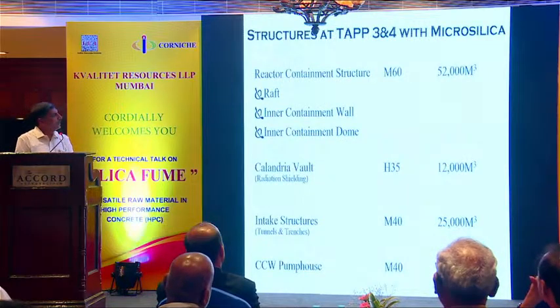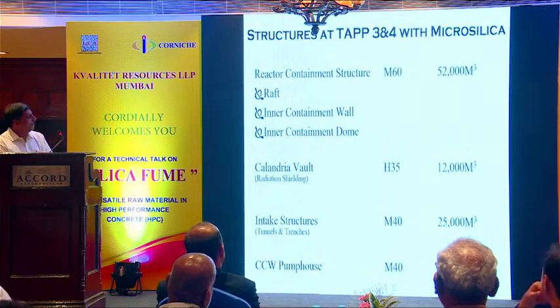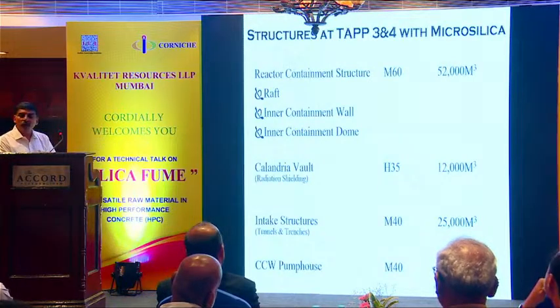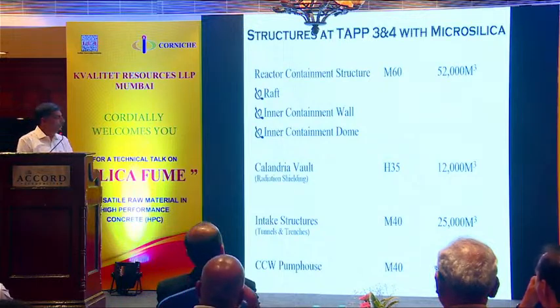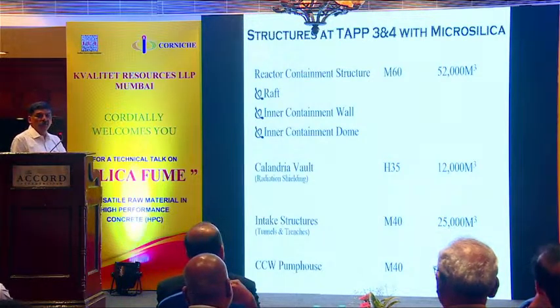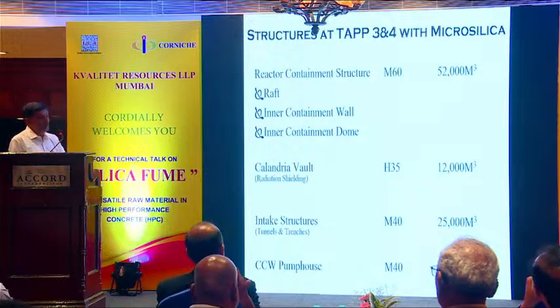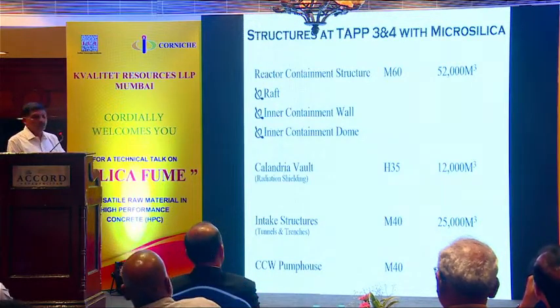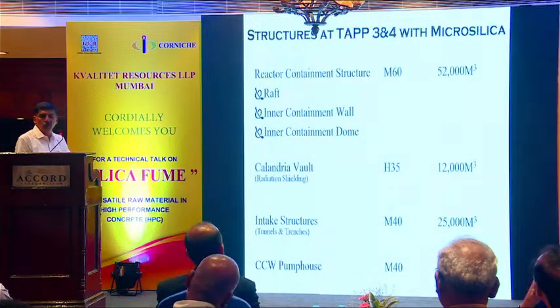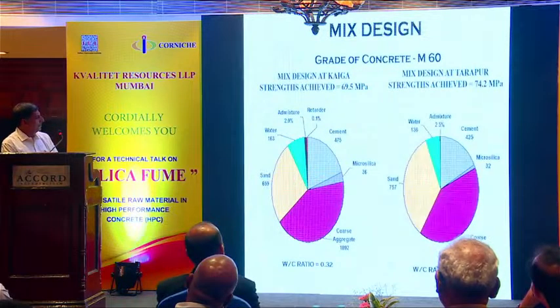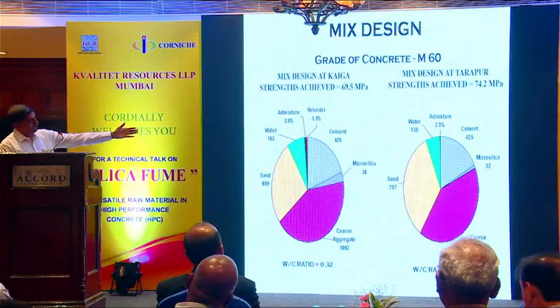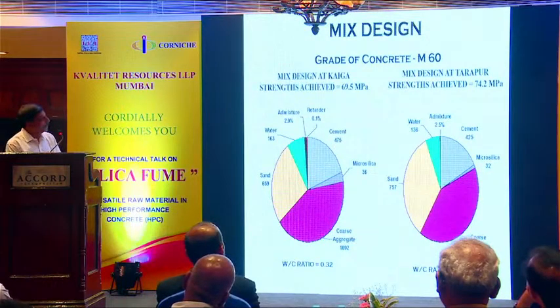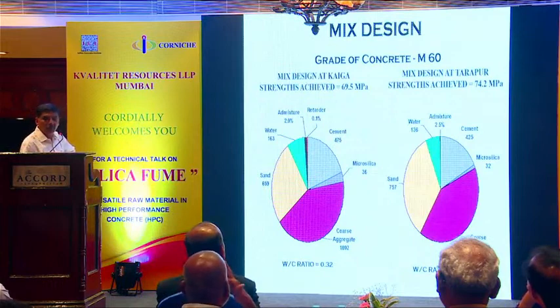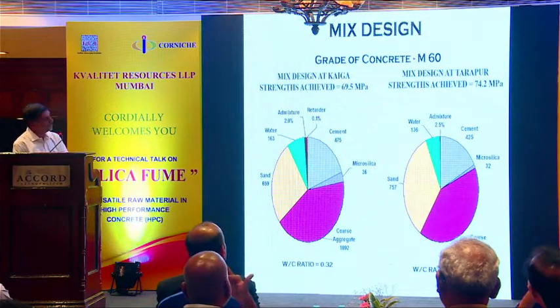For Tarapur, I think M60 for the reactor containment structure. Then the Calandria vault, high density concrete for radiation shielding. The aggregates were hematite ore. The density of the concrete there is 3.8 to 3.9. They use silica fume for 2 things: no segregation and to give impermeable concrete. Within 3-4 years, there were changes. For Kaiga and Kota, they were using 475 kg of cement for M60. Come Tarapur, I think they were able to reduce 50 kg of cement to produce the same quality concrete.